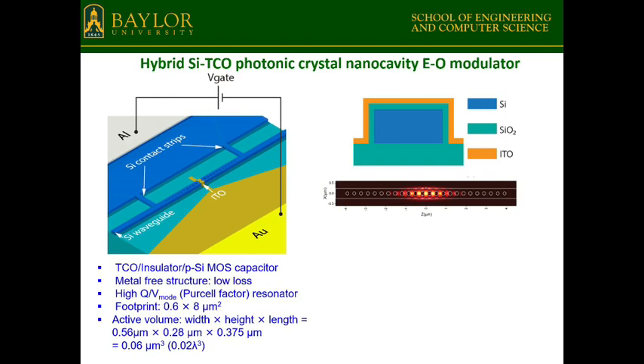So here is how we can use this transparent conductive oxide for an electro-optical modulator, as we mentioned before. This is the design of the structure. You can see this is the silicon waveguide, but we introduced periodic air holes along the waveguide. This will basically serve as a Bragg mirror, so it will reflect the light. If you have two symmetrical mirrors, it will form a resonant cavity in the center. And then you couple the light. If it's off resonance, the light will be rejected. But if it is on resonance, the light will tunnel through.